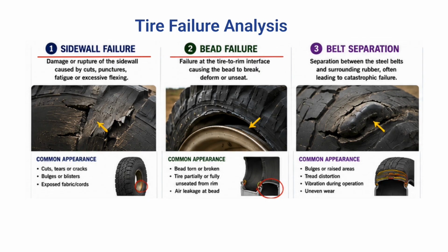The second is bead failure at the tyre-to-rim interface, which may cause the bead to deform, break, or become unseated. It often appears as a torn bead, air leakage, or partial separation of the tyre from the rim. Likely causes include low pressure, obstacle impacts, high side loads, and an incorrect or damaged rim.